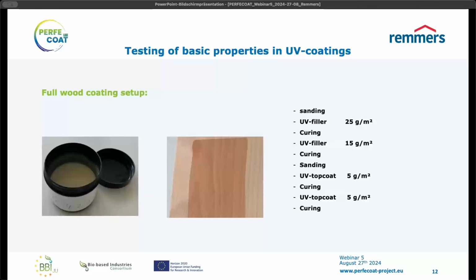And the next step, what's happening right now, and it's not completely finished yet, is to test full wood coating setups, which is described on the right side of the screen here. So what we're going to do is some sanding on the wood first, and then the UV filler is applied in 2 steps with some intermediate curing, 25 gram and 15 gram per square meter, so 40 altogether.